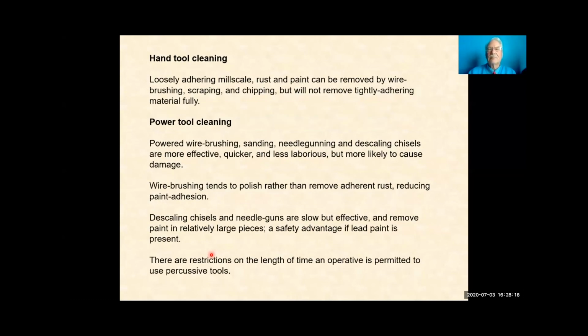The simplest and slowest technique for cleaning, but the one that's most controllable, is hand tool cleaning. So you can just use a wire brush or scraping or chipping or lightly tapping to get rid of the rust and the old paint. Of course, it's faster to use power tools like wire brushing, sanding, needle gun, descaling chisels, and so forth. But you can do a lot of damage if you've got too much power. Nowadays, we have abrasive grinders, and they will go straight through wrought iron and, of course, the non-ferrous metal. So do be very careful.